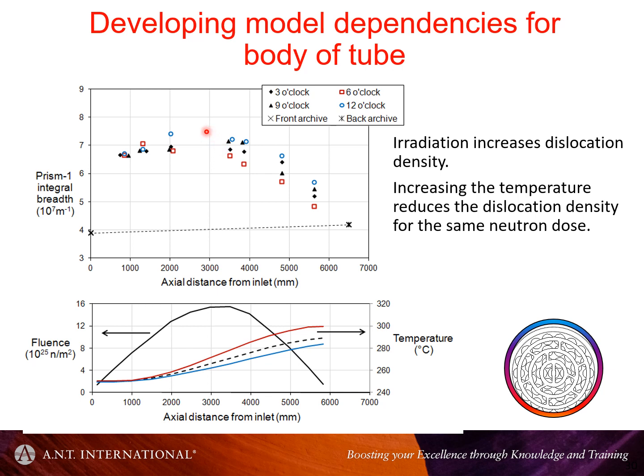So we get hardening, which basically reduces your fracture toughness, or certainly increases your DHC behavior for sure as well. And at the same location, you get mixing of the beta phase, which basically makes it easier for hydrogen to migrate within the material.